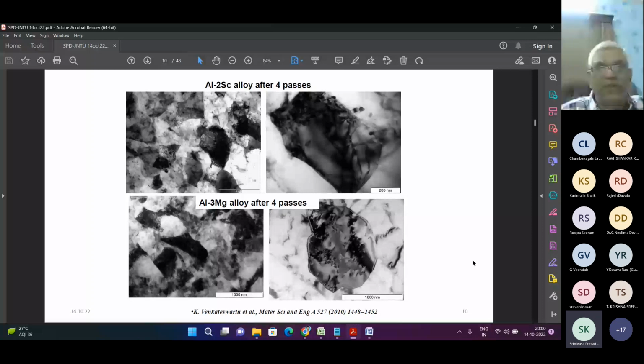And what we have done is we have tried to add scandium content. As we have seen, the aluminum-scandium master alloy is available, where aluminum with 0.25% scandium is sufficient. That means for any alloy, if you take aluminum-magnesium-silicon or aluminum-zinc-magnesium, 0.25% of scandium is sufficient. But scandium is available in the master alloy form of Al2Sc. This is a master alloy which is available.